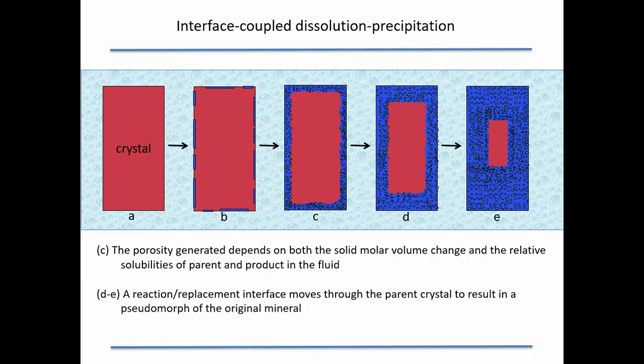As this is happening, we have the formation of porosity in the new product phase. Porosity generation depends on molar volume differences between the parent and the product, but it also depends, and maybe more importantly, on the activity or the solubility differences between the product and the parent phase at the interface. In the solution at the interface, we tend to think of dissolution rates, but they're also in water. This is the solution at the interface, which is different from the bulk.